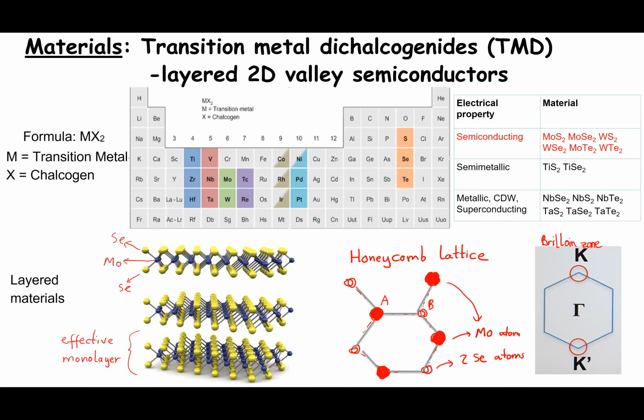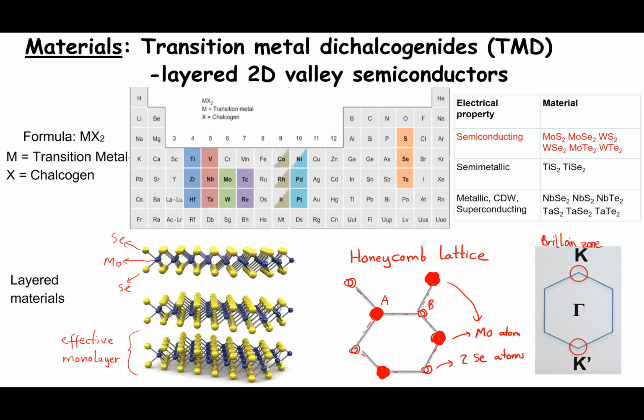So a few more words about transition metal dichalcogenides. So these are, again, these layered materials that are semiconducting. So when I talk about the monolayer, this is actually a trilayer system, a triangular lattice of molybdenum sitting in between two chalcogen triangular lattices. If you look at it from a distance, this looks effectively like a honeycomb lattice. But unlike graphene, the two sites have very different atoms, right? So in this case, the A site, say, has a metal atom, and the B site has the two chalcogen atoms.